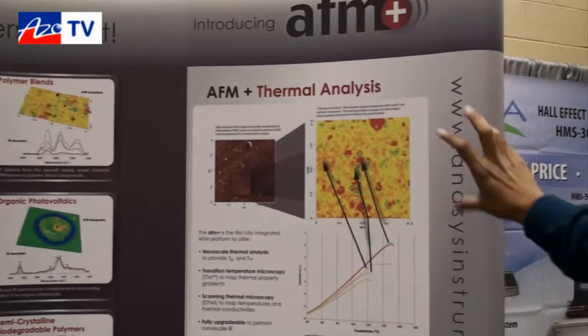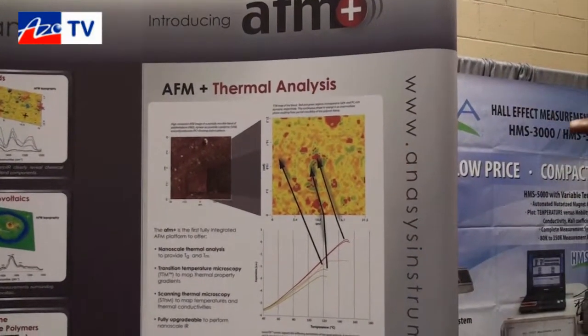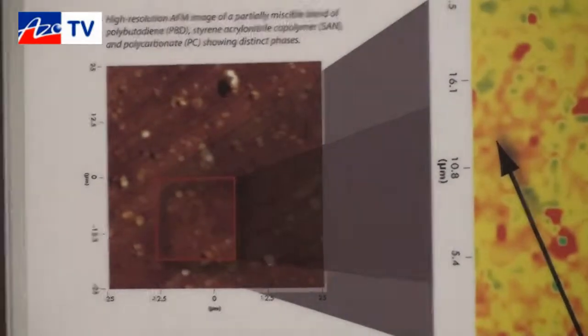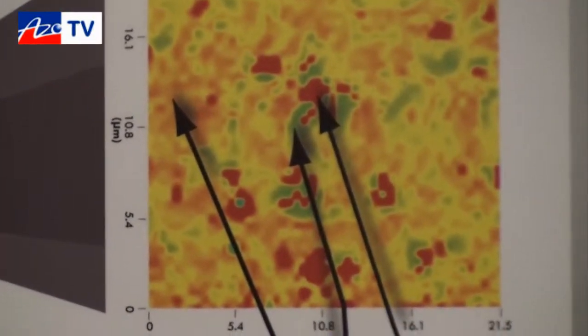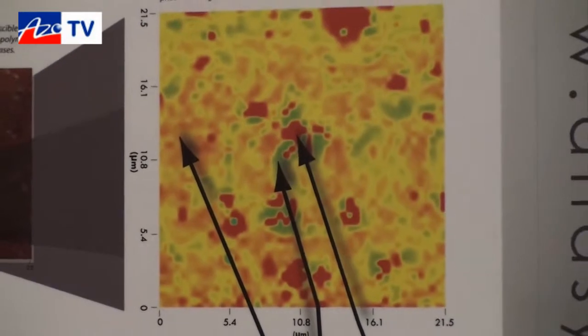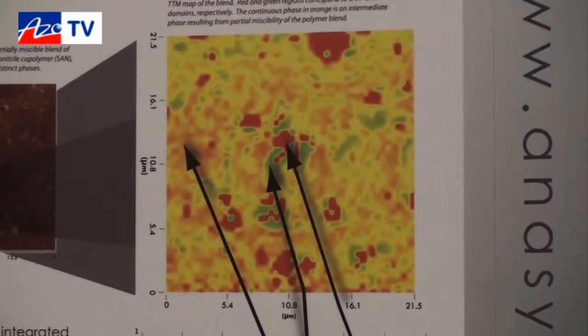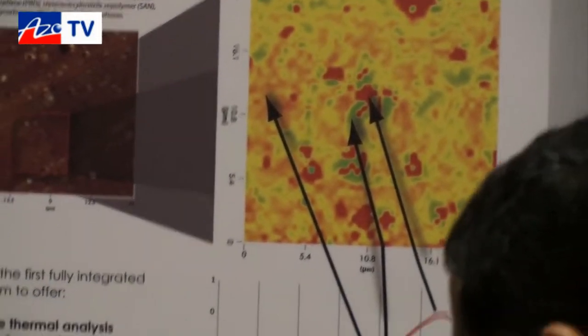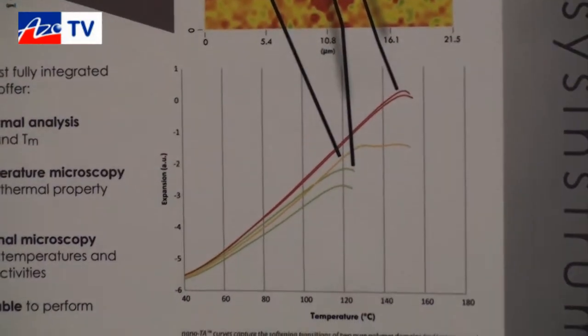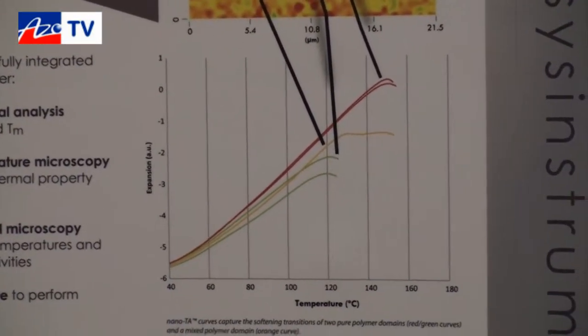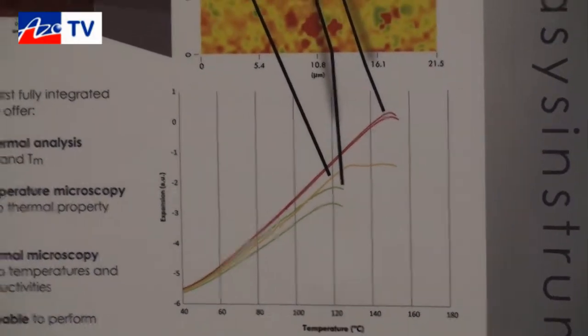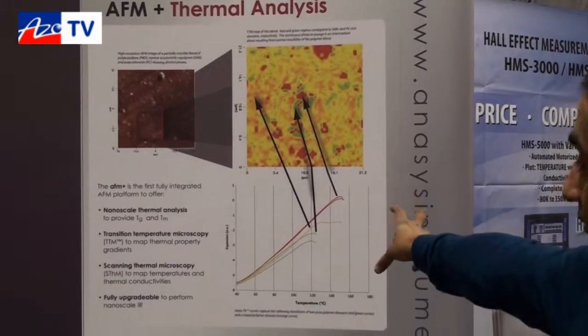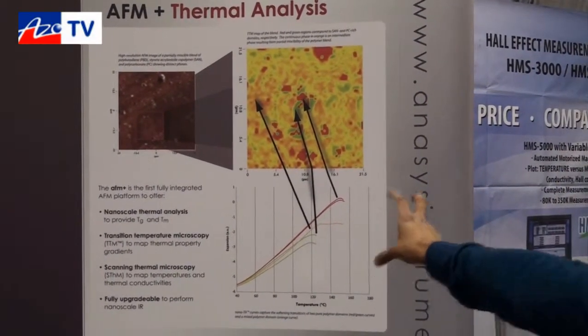So thermal analysis, for instance — once you've imaged your sample and want to understand more, you can go and heat local features with your thermal probe. The thermal probe, which is just as sharp as any regular AFM probe, heats locally and gives you important figures for polymers like Tg (glass transition temperature) or melting temperature. What you generate is a curve — a standard TMA curve — that gives you the onset of softening corresponding to Tg for an amorphous material and Tm for a crystalline material.